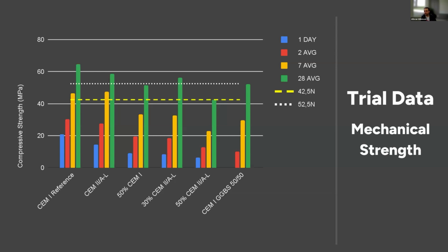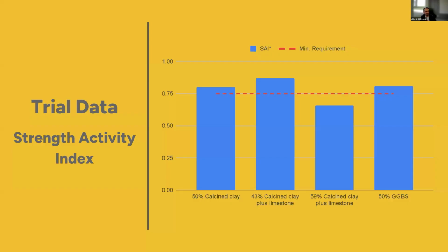Most importantly for us, we're always comparing with CEM1 and GGBS because that's kind of the industry norm, almost certainly in Northern Ireland, for a low carbon cement at the moment. And really, we're seeing the big benefits. We're achieving very similar late strengths, but that early strength development is something that's looking very promising. And any precast customers that we're talking with and trying to work with are very interested in it. Strength activity index is typically done with 20% replacement, but yeah, we're seeing really good strength activity.